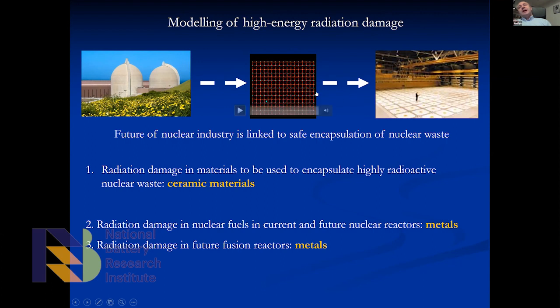Yeah, thank you. So you put this radioactive material in an inert matrix. So, for example, in a piece of ceramic. And what's shown here is a nuclear repository. Basically what we do, let's say we melt silicate, nuclear glass, then we mix all this material together, then we quench the melt. And now all these nuclear compounds become dispersed and immobilized in this matrix. And typically, this is a canister of the size of a meter by meter, and then we can put it somewhere and hope that it will remain intact and immobilized there for a long period of time.